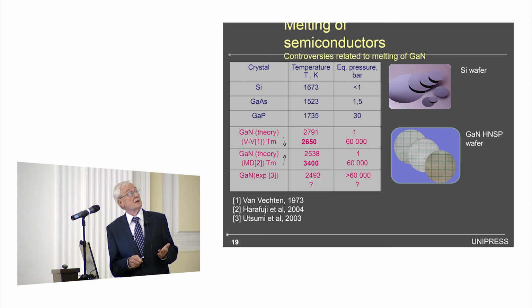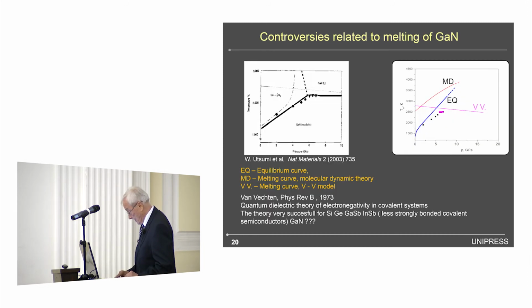There are several controversies about the melting and the pressure dependence of the melting temperature. There are two theories. One expects that the temperature of melting would go down with pressure. The other expects completely different results, that the melting temperature will increase. And there is also one report in which melting was observed at these conditions. This experimental picture shows these triangles; it is reported that at these conditions melting of gallium nitride was observed.